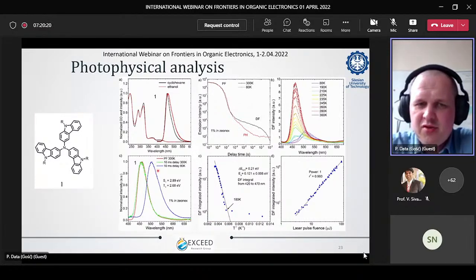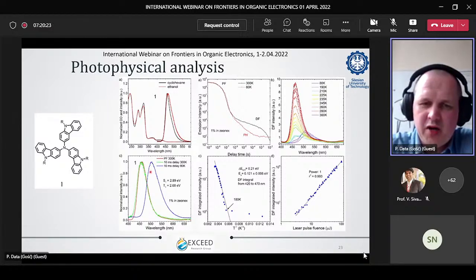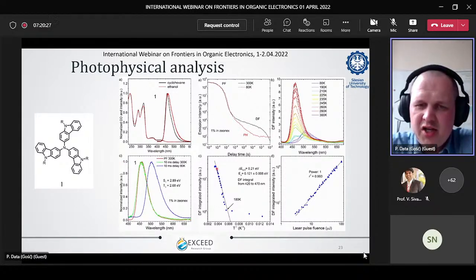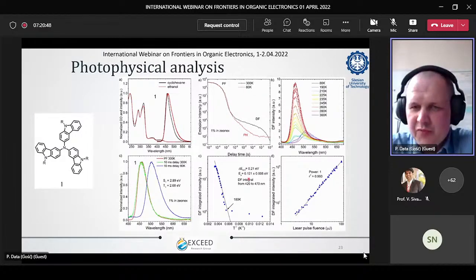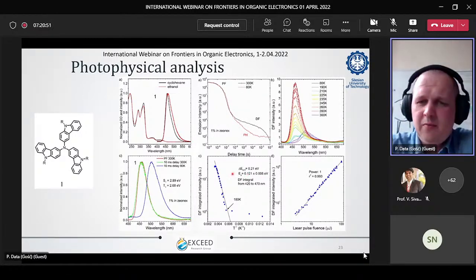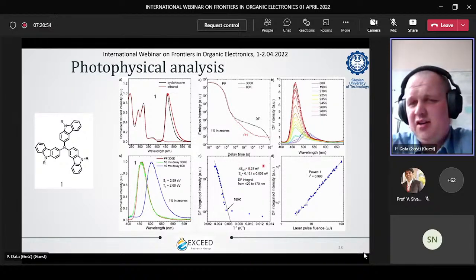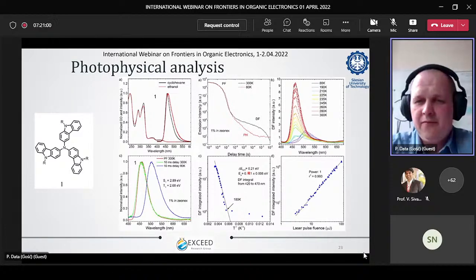We have spectra, which we integrate for delayed fluorescence, and we check how this integrated intensity decreases as the temperature drops. So you have low temperature here, high temperature here. Using this Arrhenius plot, we know the minimum energy to transfer your triplets to the singlet state. And if you look in the literature, usually it's half or even less of your ST gap, which means the actual energy to have TADF or delayed fluorescence is much lower than your ST gap.